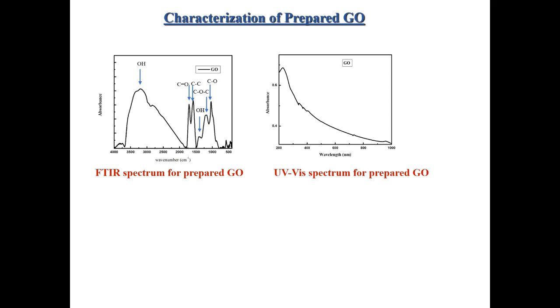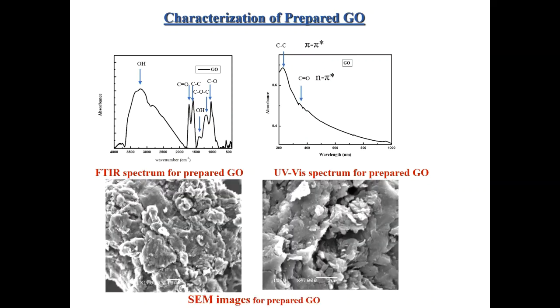Then the UV-visible spectrum of graphene oxide showed a maximum absorption peak around 229 nanometers owing to the pi-to-pi-star transition of the aromatic C=C bond, and a shoulder absorption peak around 341 nanometers due to the n-to-pi-star transition of the C=O bond. Also, the graphene oxide image showed the surface randomly aggregated as thin sheets with separate edges, a wrinkled surface, and folding.